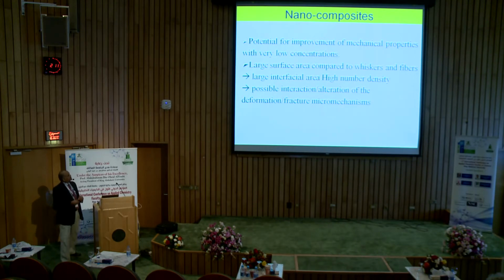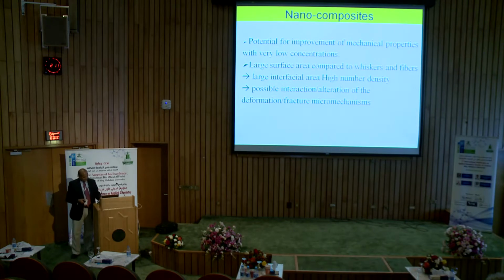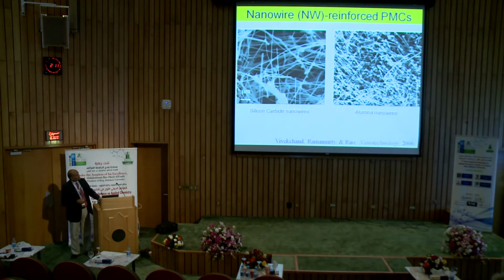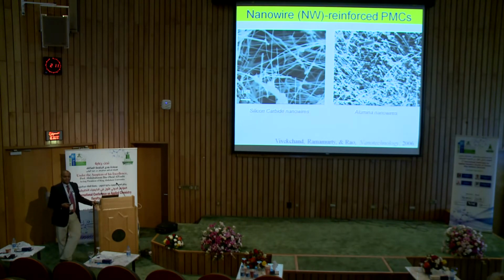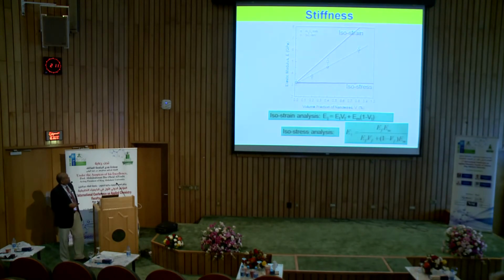One of the first things that we did was to try to measure mechanical properties of nanocomposites, where we put nanomaterials, and this I will go quickly. So for example, one of the first ones we tried to do, this is way back, was silicon carbide and alumina nanowires. So these materials have very large surface to volume ratio. So as a result, you get phenomenal improvements.